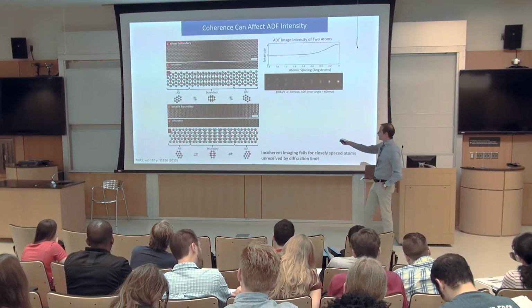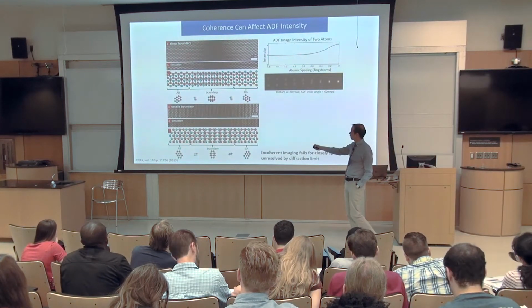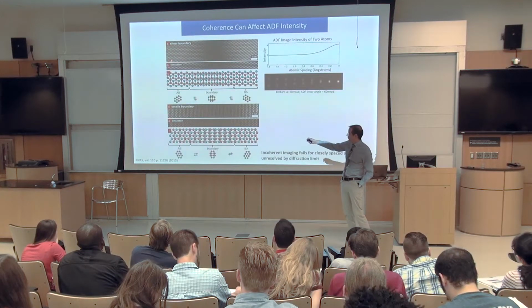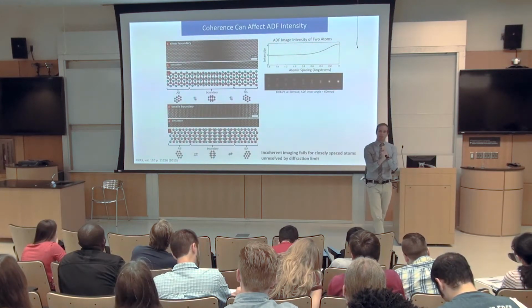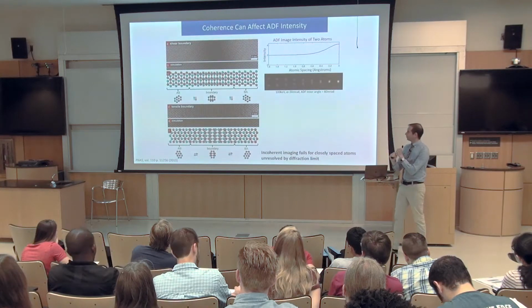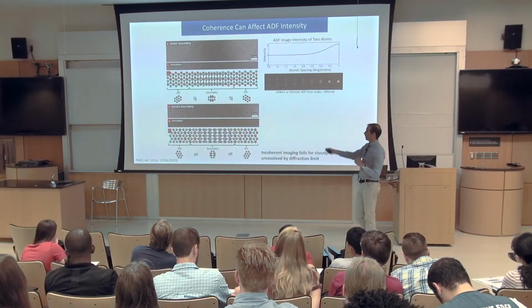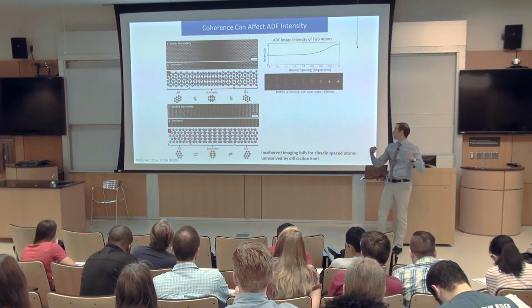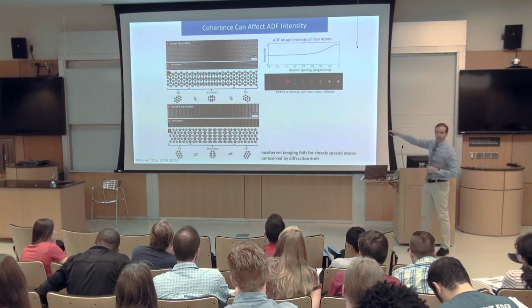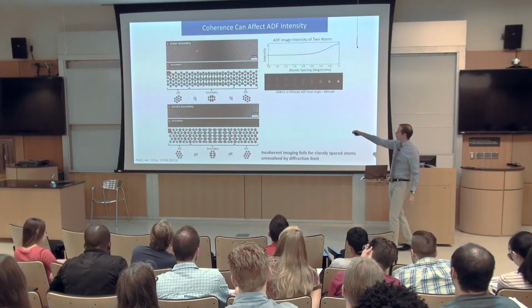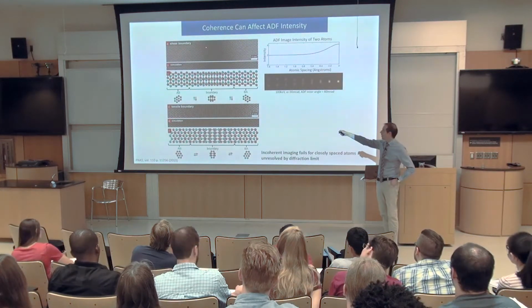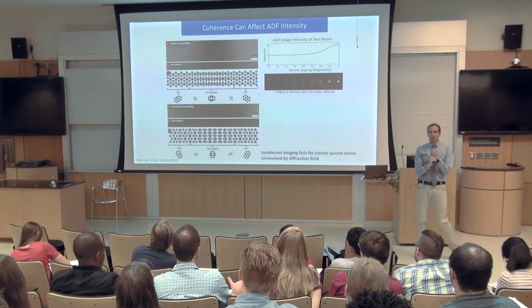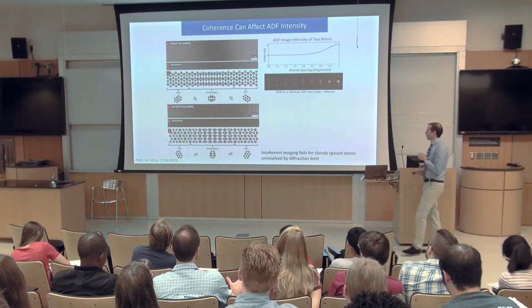And this is illustrated experimentally in this strained bilayer graphene system where the bright atoms you see here correspond to 2 atoms on top of each other in Bernal stack graphene. So in Bernal stack graphene, every other lattice site has 2 atoms atop each other. And then we're now pulling those atoms apart. So we're running this in reverse. And what happens is the total intensity decreases. And then it returns back to a maximum when it goes back to atoms being atomically registered atop each other.